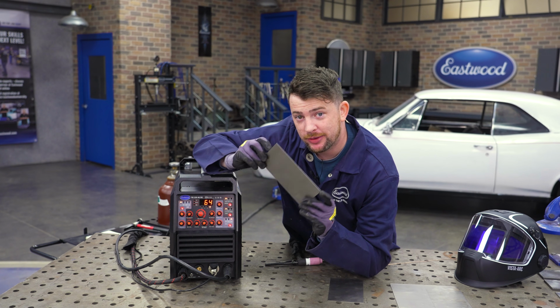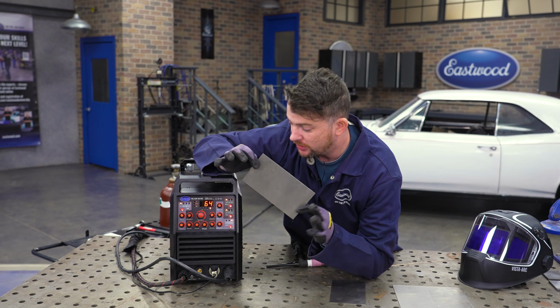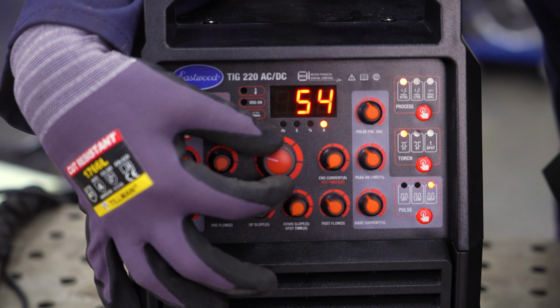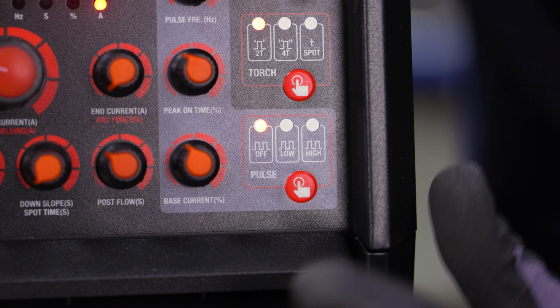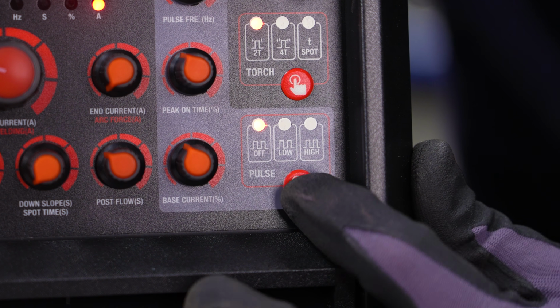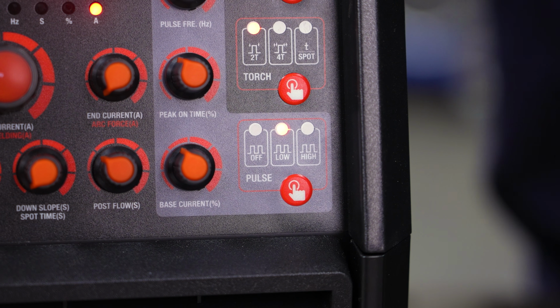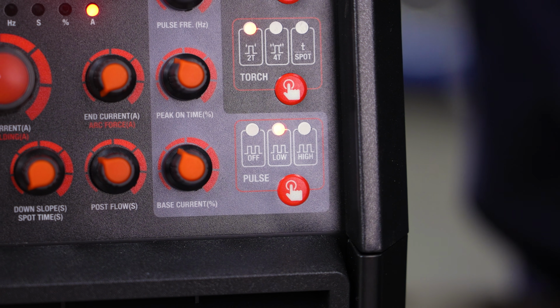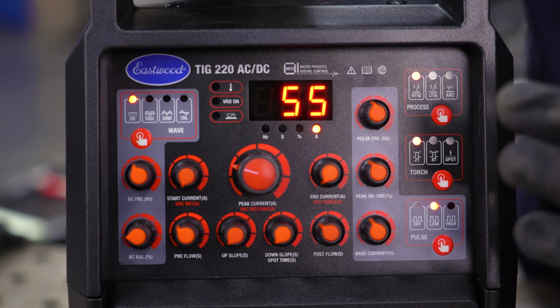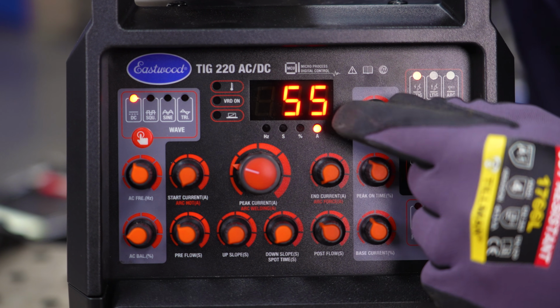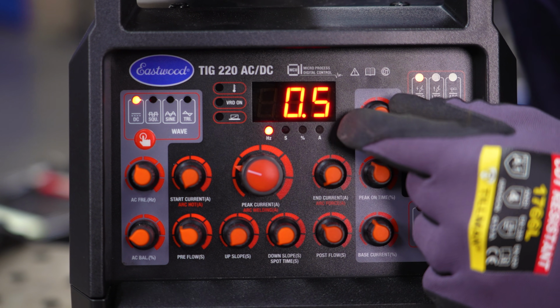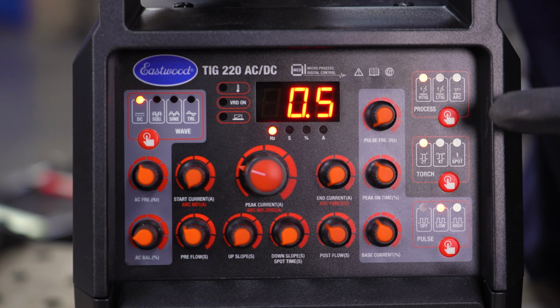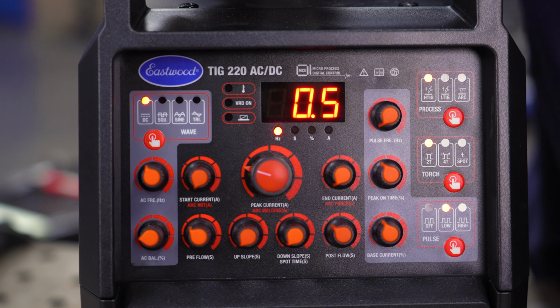We're going to begin with thin sheet metal. This is steel, and we're going to use a DC setting of 55 amps. Now I'm going to set the pulse function to low, which will give me a range of about 0.5 hertz up through 20 hertz on this machine. First knob I'm going to worry about is the pulse hertz. So I'm going to set the hertz all the way down to 0.5. That means I'm going to get 1 pulse every 2 seconds.